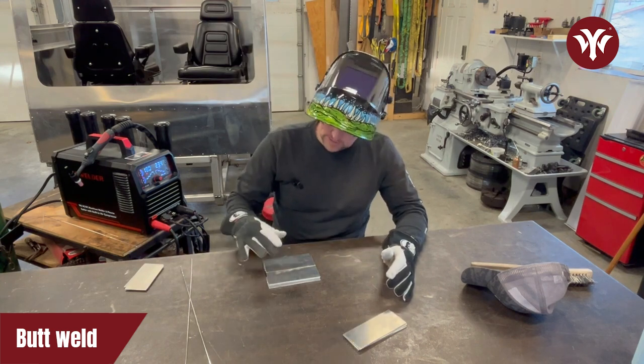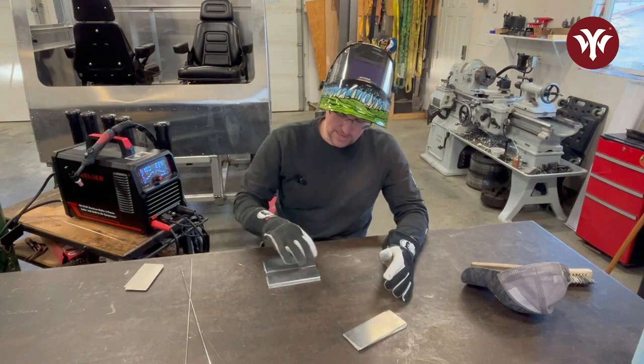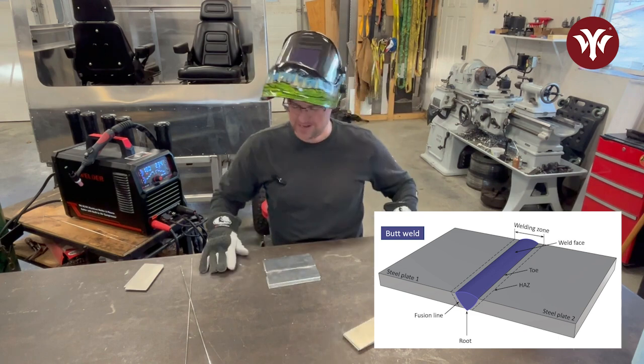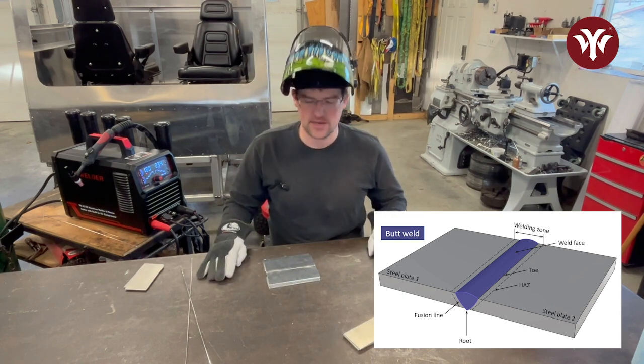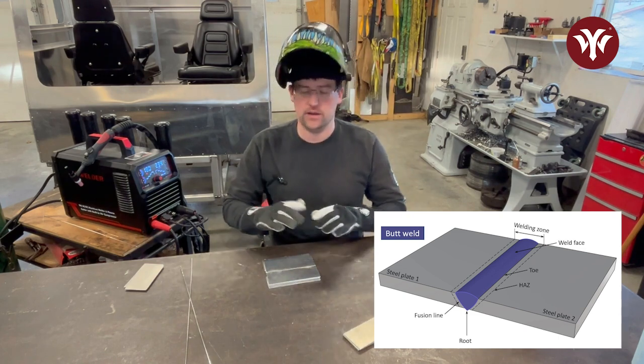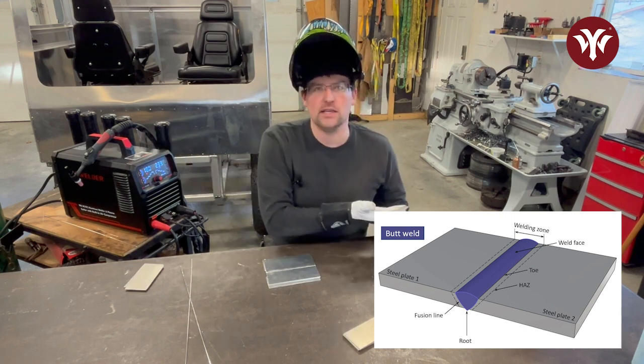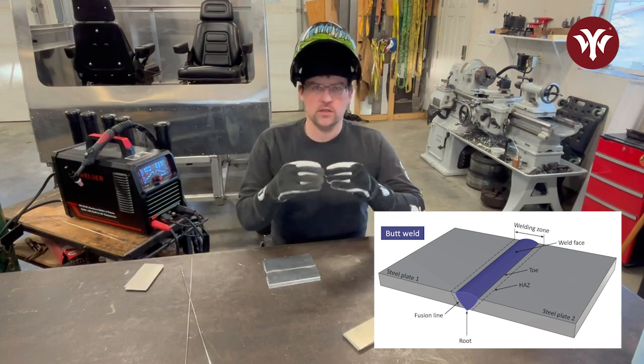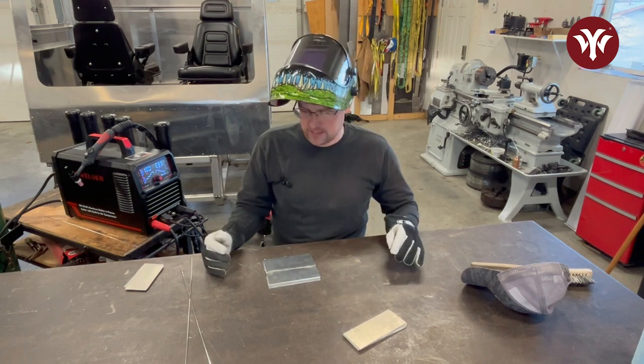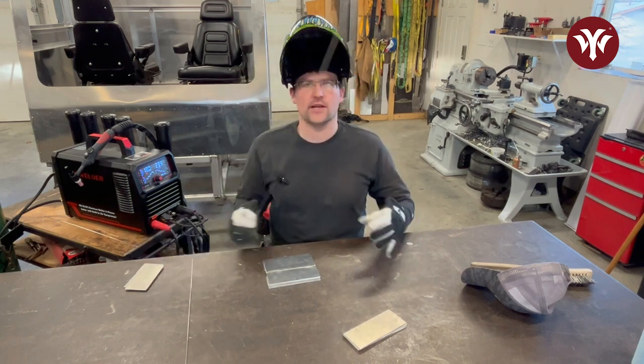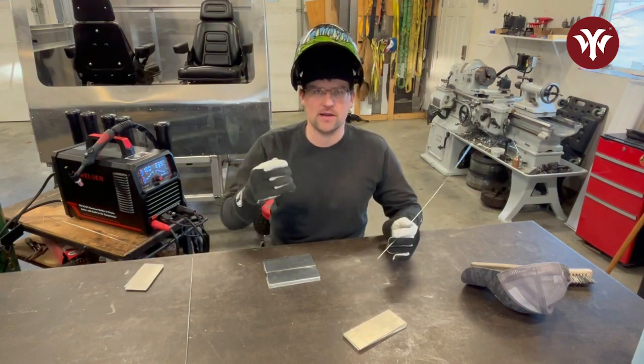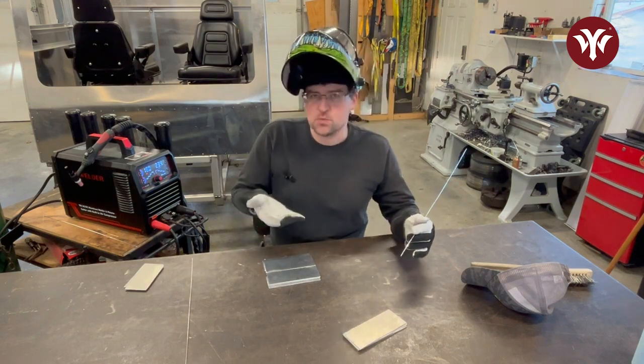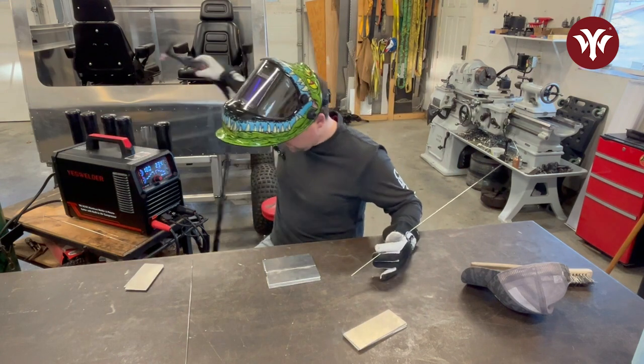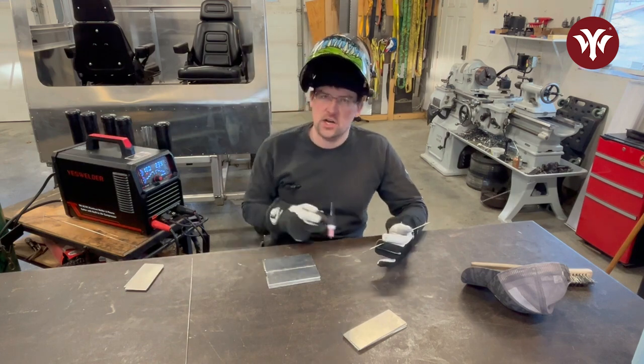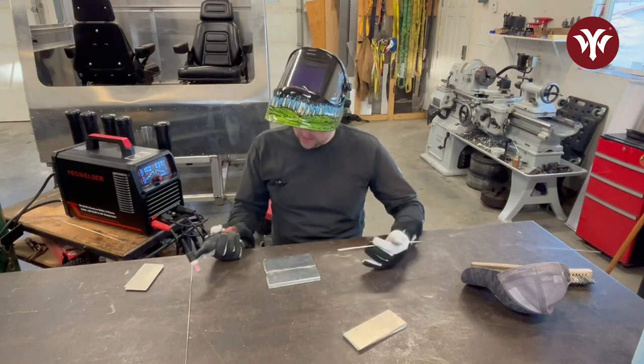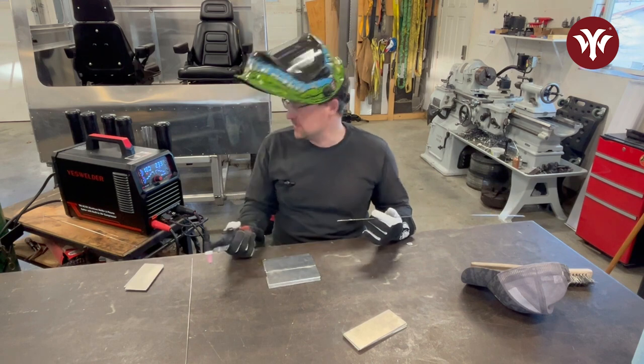And if you've noticed, what I did was space my two weld coupons off this table. This is a 1/2 inch thick steel table. If I laid those down right on there, it's going to really pull heat out of the weld joint right where they meet. And it can give you a little problems trying to get the molten puddle and the penetration you need. So I'm just going to space that up a little bit. I'm going to go ahead, I'm going to tack the start and the finish, and then I'm going to get in here and lay a bead down.